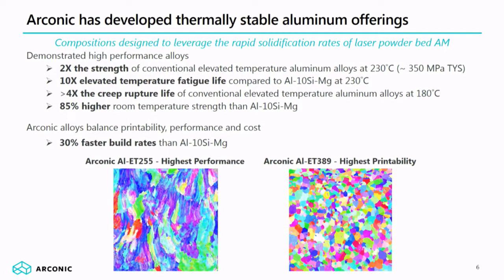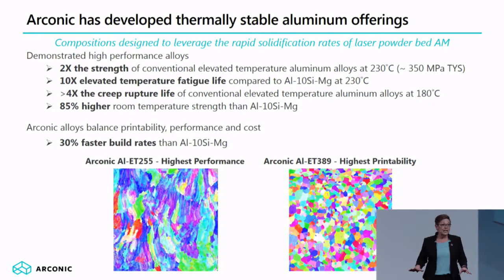Thank you, Sean. Arconic has developed two thermally stable aluminum alloys specifically for additive manufacturing. Both of these alloys require the rapid solidification rates associated with laser powder bed processing and cannot be made by conventional ingot metallurgy methods. In fact, by leveraging the rapid solidification rates, it enables us to introduce alloying additions that really help us expand the performance envelope, especially at elevated temperatures. Our approach has been to balance performance, printability, and cost. Ultimately, this gives our customers the ability to choose the alloy that best meets their needs.